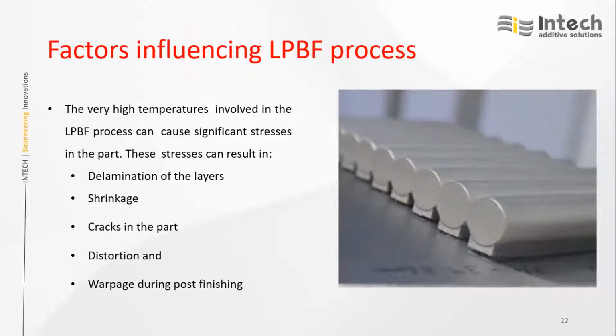The reasons behind the delamination and the major problems which we get in the process are delamination of the layers, shrinkage, cracks in the part, distortion, and warpage during post processing. The reason behind this is maybe the process parameters, maybe bad machine preparation, and maybe the selection of base plate is not suitable for the given material.